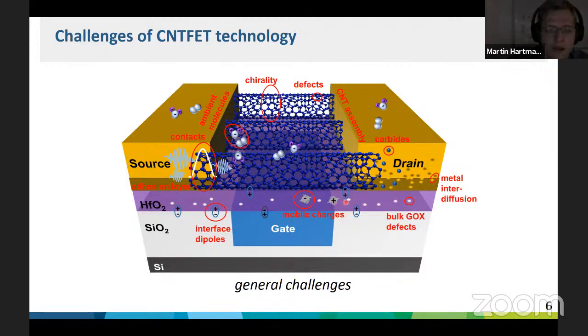And you really need to control them in order to facilitate the best properties of the tubes. Yes. And then you also need to take into account whether you do some pre-treatments. When you do some annealing, for example, afterwards, this enhances the metal diffusion, but also carbides can form. Okay, so you somehow decompose the CNTs a little bit, the carbon goes into the metal, and you can either form direct bonds to the metal, or you change again the work function of the metals. So this is again something you need to keep in mind.